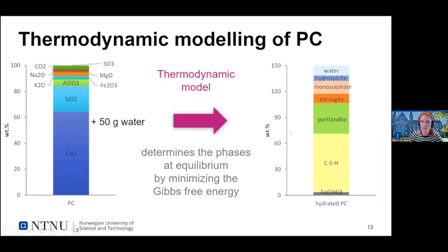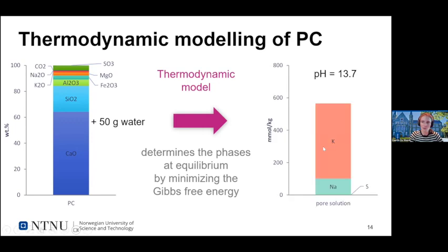And what you can see here, this is actually gram per 100 grams cement. You get quite a bit of CSH, some Portlandite, ettringite, monosulfate, hydrotalcite, and water. So you get the phases that will form at equilibrium. And you don't only get the solids, you also get the composition of your pore solution. So here you have it in molality.